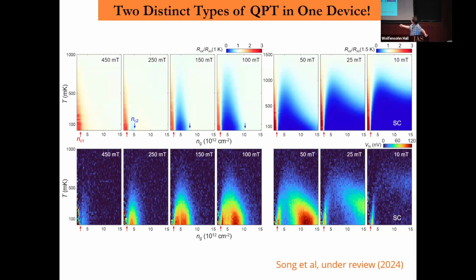So the same resistance data in the top row, resistance as a function of density and temperature. You see how we apply magnetic field, from zero, very small field, to high field. You see the transition happen at the critical point. The superconductivity develops around the critical point.